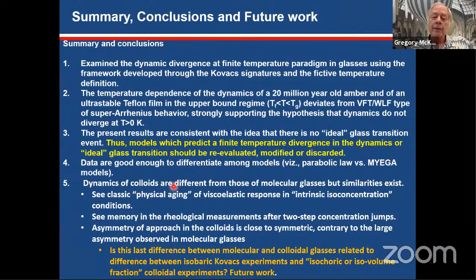And then the dynamics of colloids are somewhat different from those of molecular glasses, but similarities exist. We see the classic physical aging of the viscoelastic response in the intrinsic isoconcentration conditions. We see memory in the rheological measurements after two-step concentration jumps. And we see that the asymmetry of approach in the colloids is close to symmetric, contrary to the large asymmetry observed in molecular glasses. And is this last difference between molecular and colloidal glasses related to the difference between isobaric Kovacs experiments and isochoric or iso-volume fraction colloidal experiments? And this is something that has to be looked at in the future.